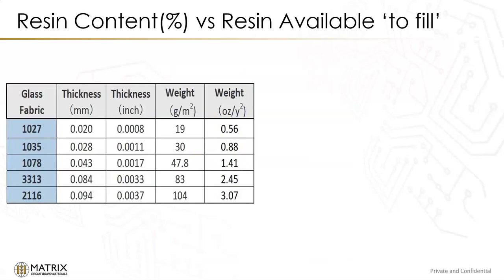So again, this is another way to look at that same chart we were at with the glass fabrics and the thickness values for each of the glass fabrics. And here's the relative weight for each of them, both in grams per meter squared and ounces per yard squared. And you can see that the 1027 is a very lightweight glass, at 0.56 ounces per yard squared, compared to the 1078, it's almost 3 times less. So it's an important factor because when we start talking percentages, those become very significant.